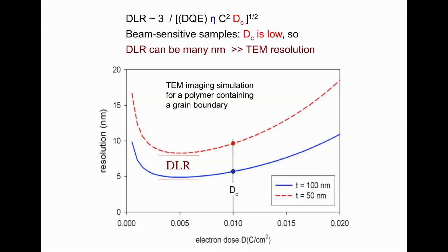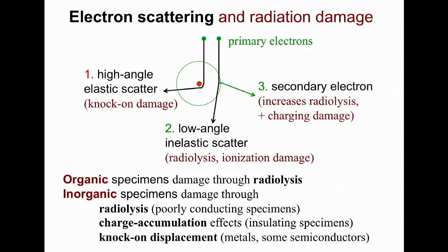To understand the differences here, we need to briefly consider the mechanisms of beam-induced damage. If a beam electron passes within a few picometers of an atomic nucleus, it is elastically scattered through a large angle and can transfer enough energy to the nucleus to displace the atom and destroy the original atomic structure. This knock-on damage is most evident in electrically conducting specimens, but is rather slow because the probability of high-angle scattering is small. This slow damage can even be largely eliminated if we can reduce the accelerating voltage, and therefore the kinetic energy of the beam electrons, below some threshold value, such that the maximum energy transfer is less than the atom's binding energy.